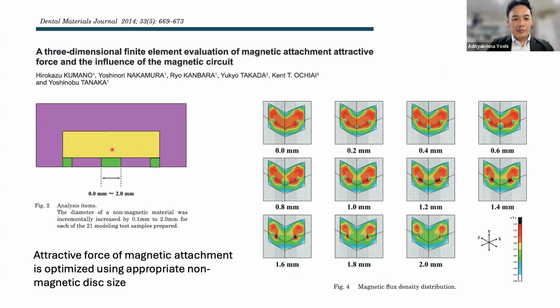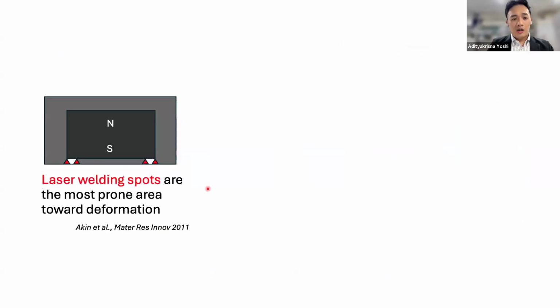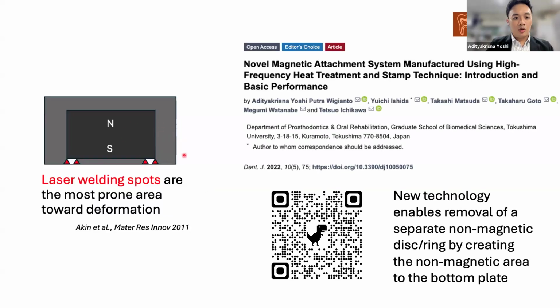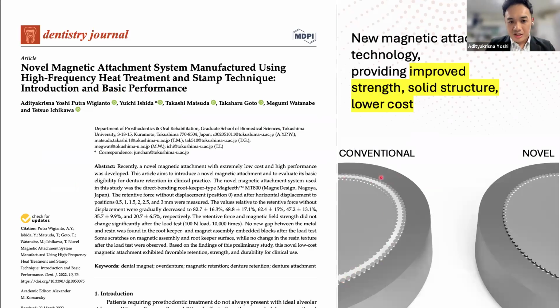Further development is the modification of the non-magnetic ring, which also influences the distribution of the magnetic field, as in these diagrams, and the efficacy of the retentive force. However, the laser welding spots are also reported as the most vulnerable part of the magnet assembly. Because it provides the connection structure, throughout cycles this connection can deform if excess wear or force is applied, or if, for example, the surrounding fixing resin or cement accidentally gets onto this surface, which can also deteriorate the welding surfaces.